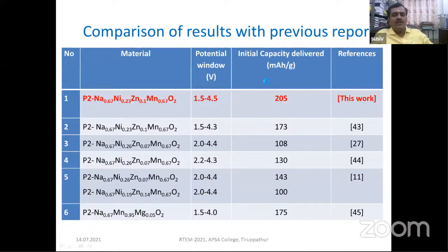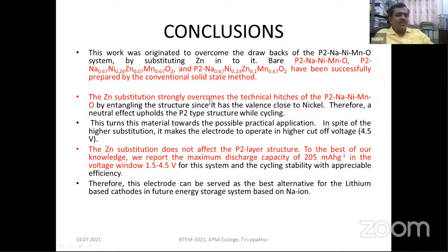it gives around 205 milliampere hour per gram. Whereas with 0.07, it just drops to around below 200. So it can be used in the potential window 1.5 to 4.5. It has been compared with several researchers' earlier reports, and we stand first. That Zn substitution strongly overcomes the technical hitches of this P2 type NaNiMnZnO material, entangling its structure by means of the valence close to nickel, and it holds the P2 type structure upon cycling.